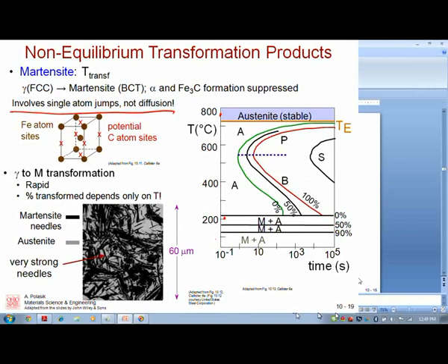We're moving from a dense to a less dense pack, so in that movement there are going to be teeny tiny pockets of austenite, but martensite forms as these needle shapes. But the important thing that I want you to know about martensite is it's very hard, it's diffusionless, and it's not an equilibrium phase.